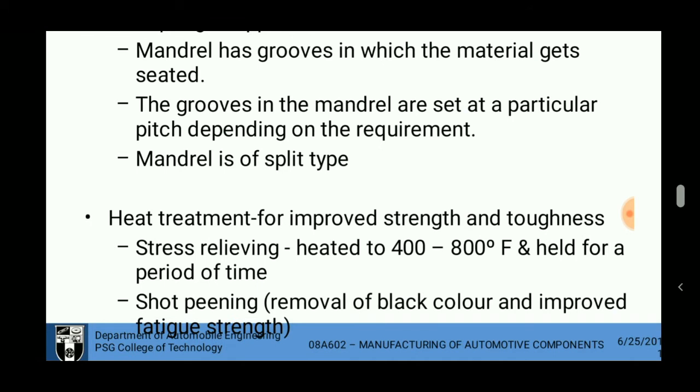Then heat treatment is used for increasing or retaining the properties of this spring and stress relieving, that is heated to 400 to 800 degrees Fahrenheit and held for a period of time so that it will not lose its suspension or spring property.